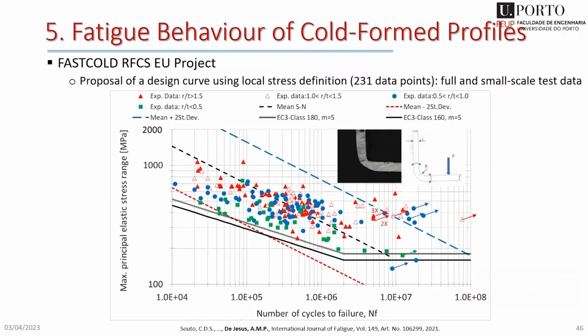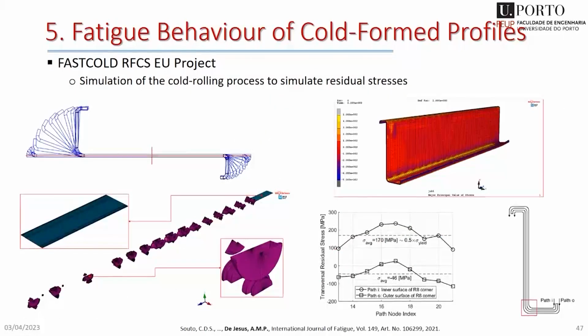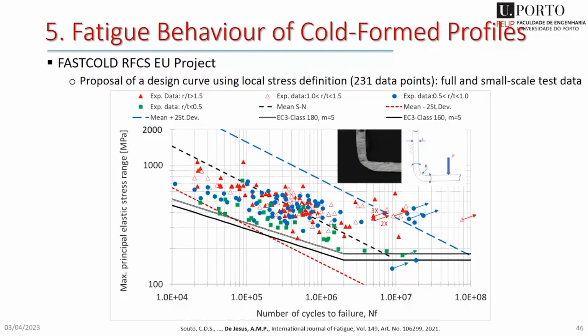The most important message is that in this kind of thin sections, we are talking of fatigue cracking in the corners. So the corner geometry will always be a key geometric parameter. So we must be careful about that. Be careful about manufacturing, because if you are lower than R over T of 0.5, I cannot say that we can use these design curves. Of course, I forgot to mention, here we are already using a local elastic stress in the corner of the profiles, which is a local stress definition.